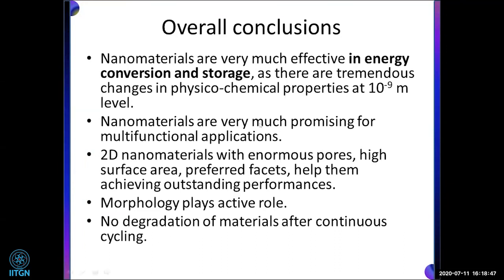From the same material, I got very good energy storage application. And there is no degradation of the material after continuous cycling, because we have tried photocatalytic or electrocatalytic for 50 hours, 100 hours, and for energy storage, for supercapacitor, we have done 40,000, 50,000 cycles.